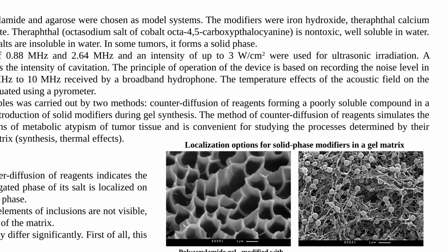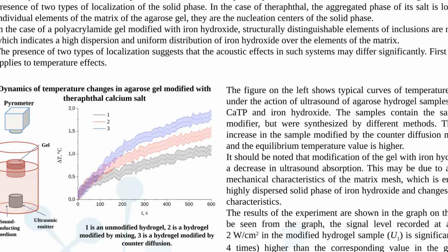This indicates a high degree of dispersion and a relatively uniform distribution of iron hydroxide throughout the elements of the polymer matrix. The presence of these 2 localization patterns suggests that their acoustic effects can differ substantially. This is particularly important for temperature effects.